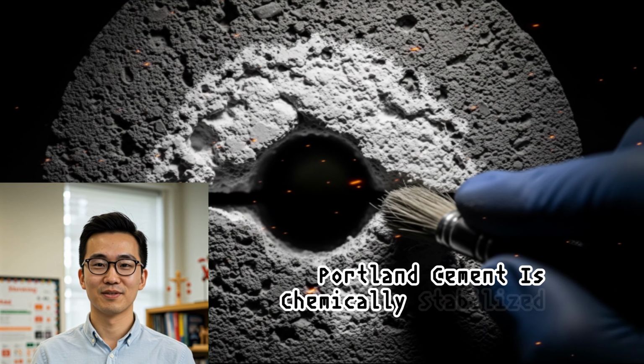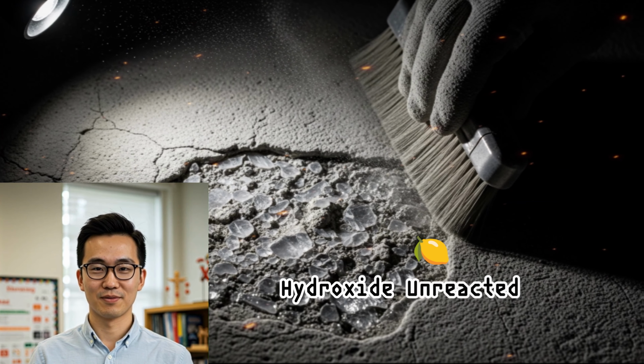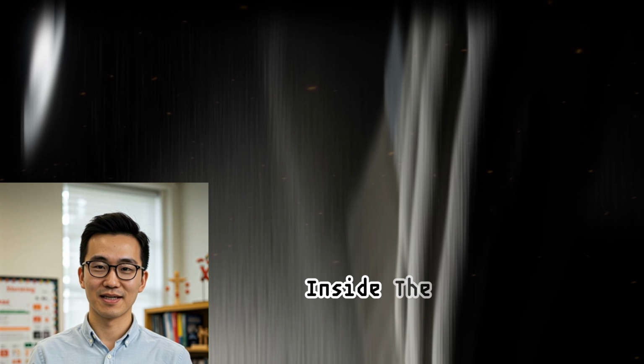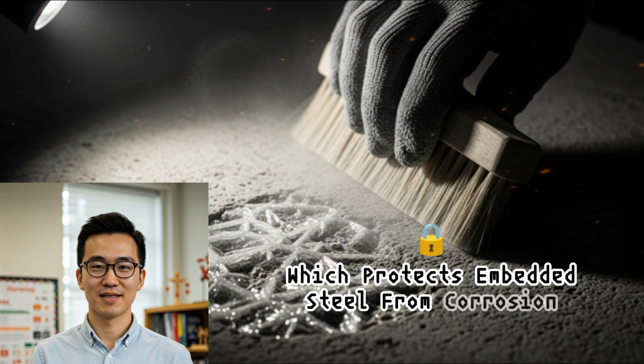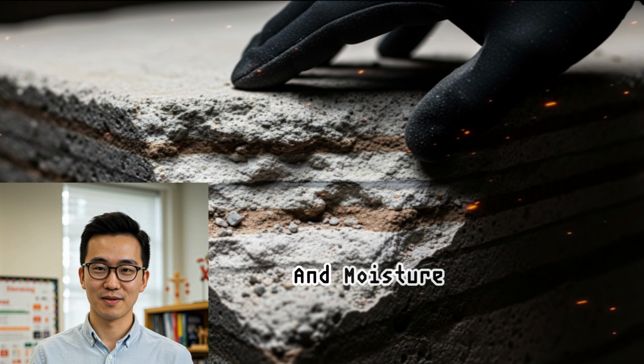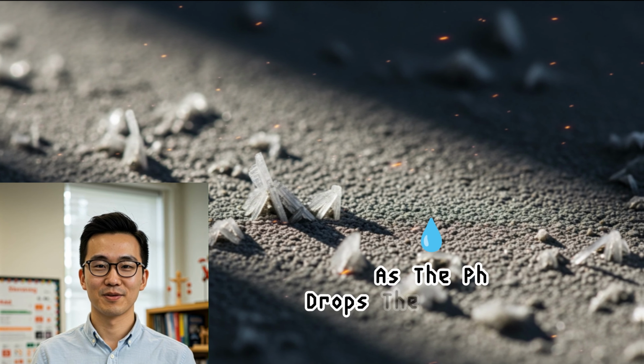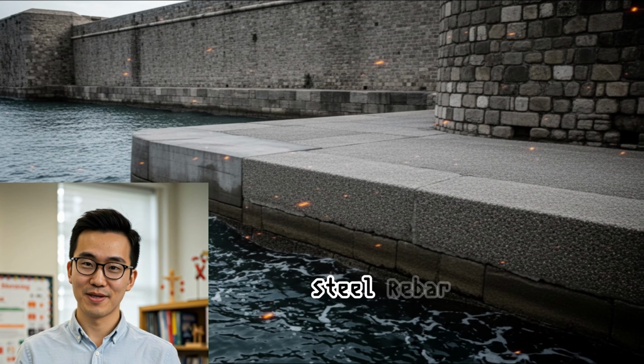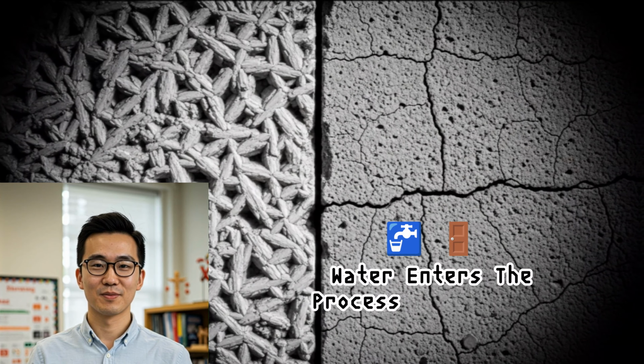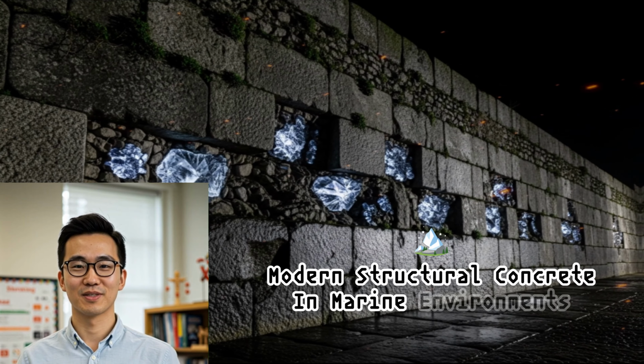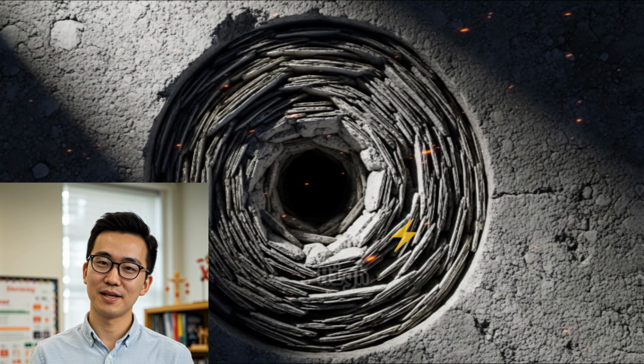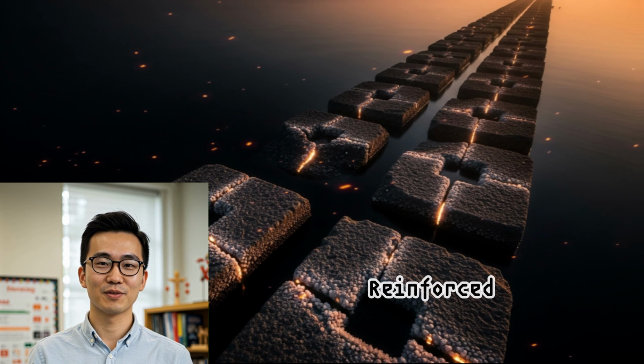Portland cement is chemically stabilized by calcium hydroxide, unreacted lime that maintains a high pH environment inside the structure, which protects embedded steel from corrosion. But seawater, carbon dioxide, and moisture gradually consume that calcium hydroxide through a process called carbonation. As the pH drops, the protective environment disappears. Steel rebar expands as it corrodes. The surrounding concrete cracks. Water enters. The process accelerates. Modern structural concrete in marine environments isn't decaying despite its design. It's decaying partly because of its design. High strength, fast curing, steel reinforced, in an environment that systematically attacks each of those properties.